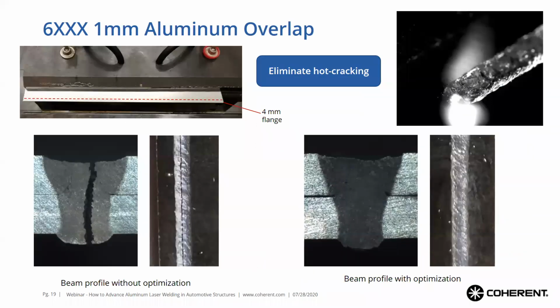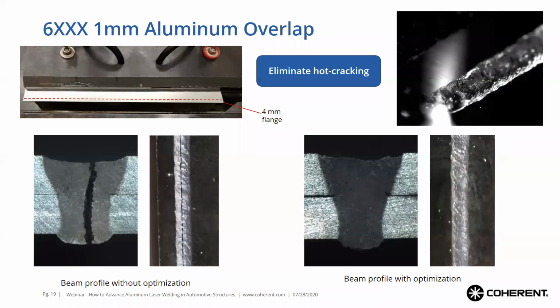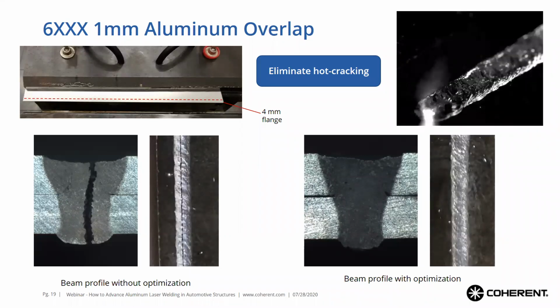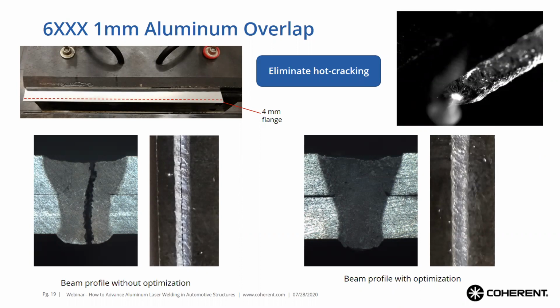So starting with an aluminum overlap here in the 6000 series. This is a 1 millimeter aluminum overlap where, top left of the screen, you are looking at a weld done 4 millimeters away from the end of a flange. And most OEMs would typically recommend being 6 to 8 millimeters away from the end of the flange. Problem being, if you look at the bottom left of that image, area where we used either a Gaussian or flat top fiber laser, so a standard fiber laser available on the market, you see that the issue with the aluminum, being that it conducts heat really well, is that on one side of the flange, you have the material running and being heat sinked easily, but on the other side of the flange, the heat has nowhere to go. So you end up with a very high temperature gradient right about the weld as the material cools.